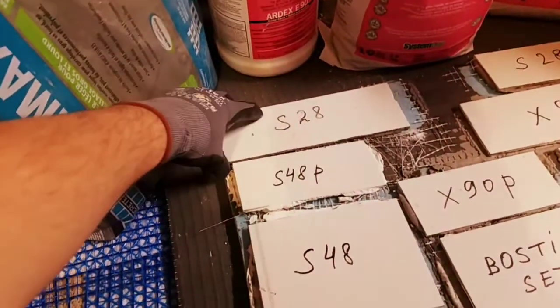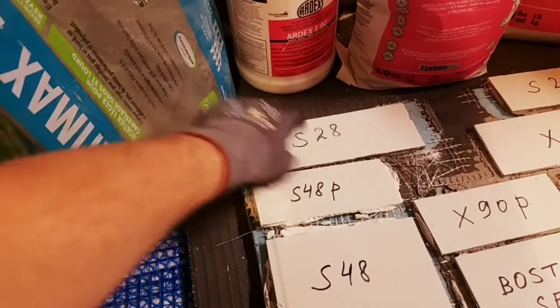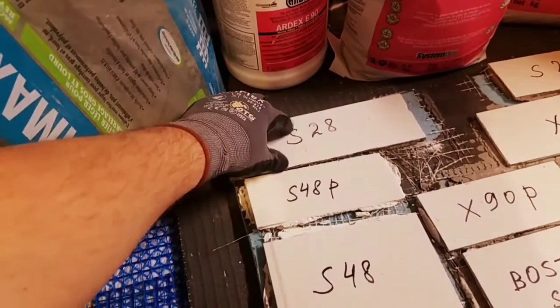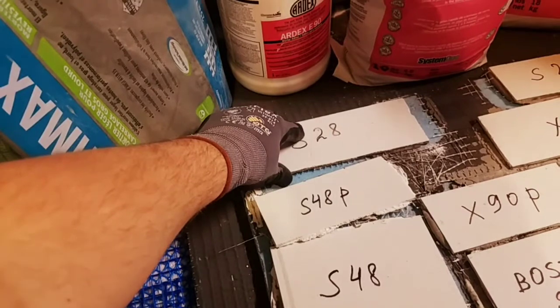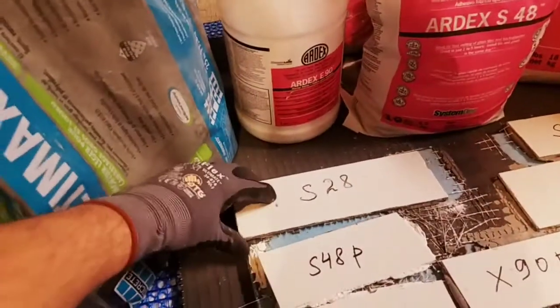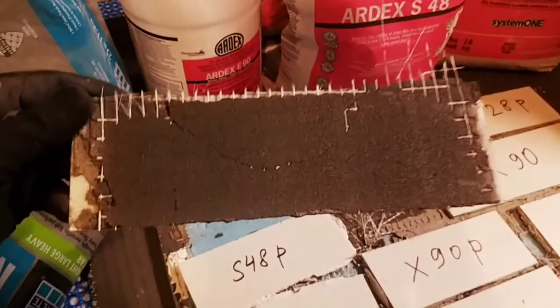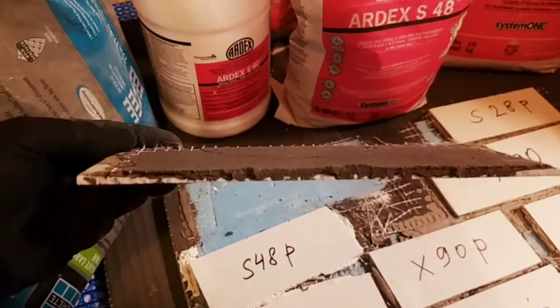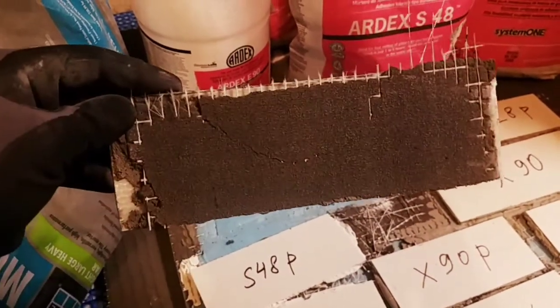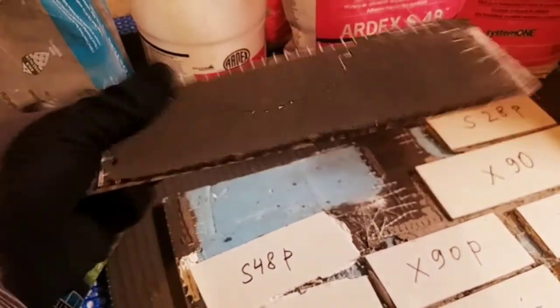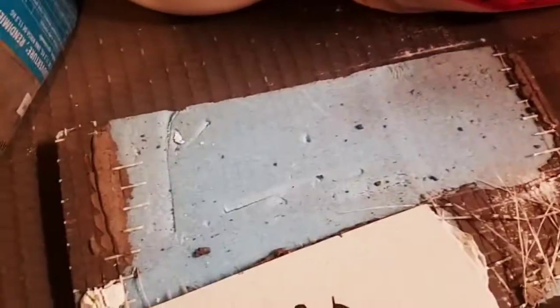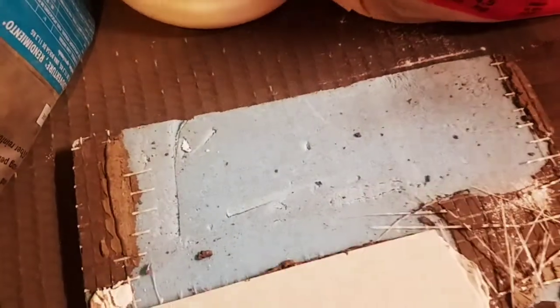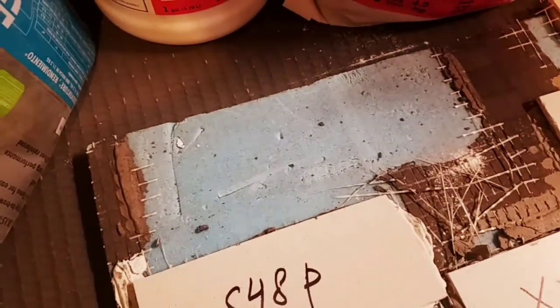It was Ardex S28. It was adhered directly to resin backing, and after 7 days it shows such a great bond to this resin backing. As you can see, the top coat of the Wedi panel came off with this sample piece.